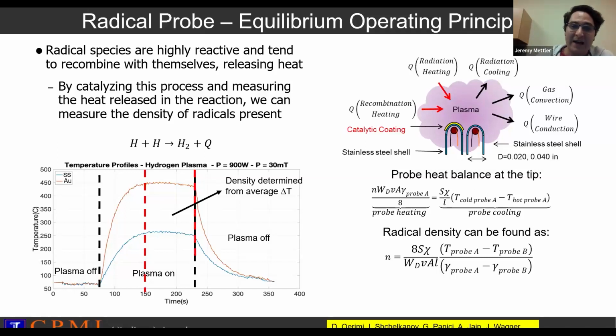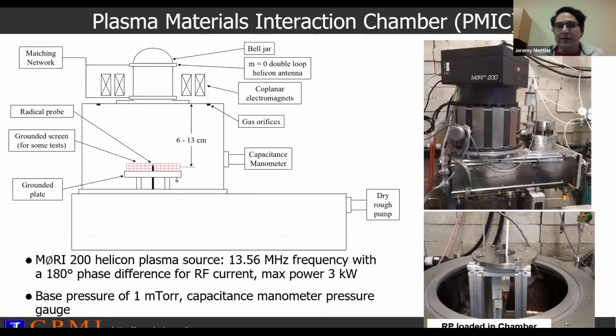But despite these caveats, we set out to try to apply this concept to fluorine. And so to that end, we built a chamber that we could introduce a couple of different fluorine-containing gases in, both SF6 as well as NF3. And we have a plasma source on the top, a helicon plasma source. And we can run this chamber at a variety of different pressures and flow rates and plasma powers.